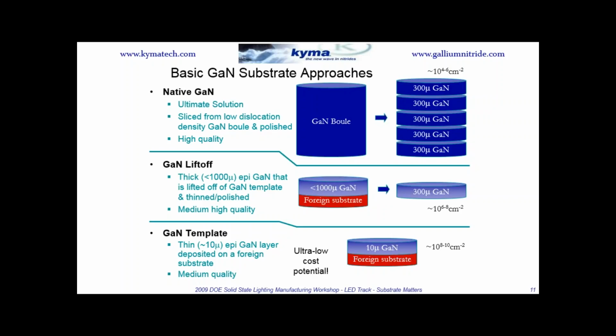Like for instance, Sumitomo Electric, at least according to what's in the open literature, they start with a 111 gallium arsenide substrate that's pretty cheap, because you're throwing it away after each growth, to my understanding, and then they grow less than a millimeter of GaN, and they yield 1 substrate from that. And there's similarly, I think Hitachi Cable was starting with sapphire, and Kyma would start with sapphire, and we do this today.